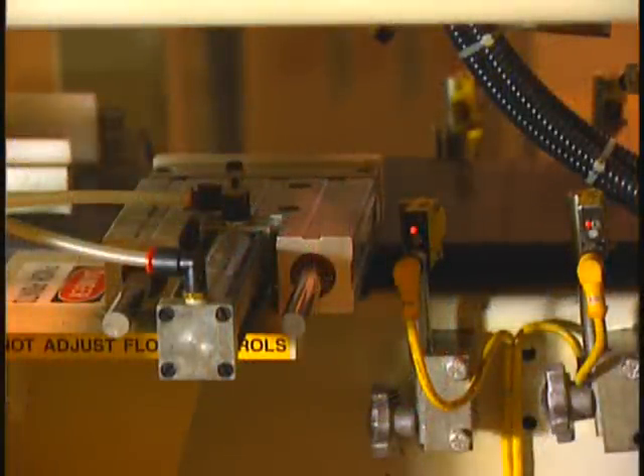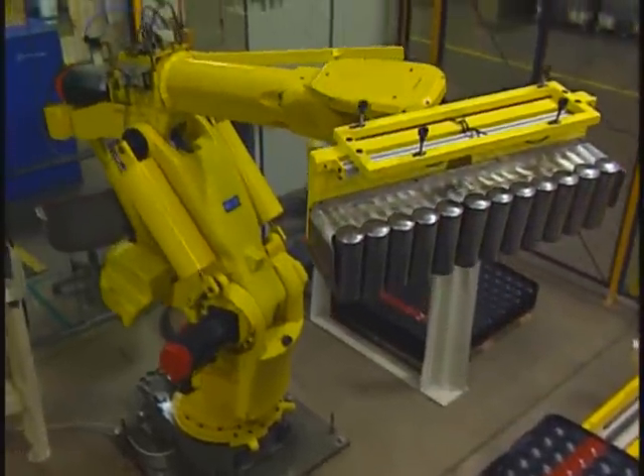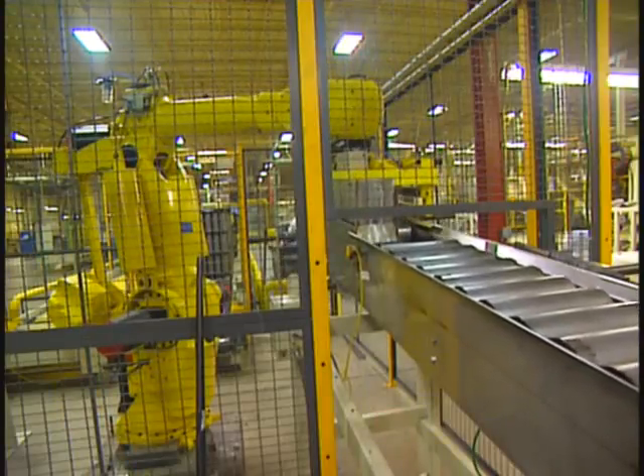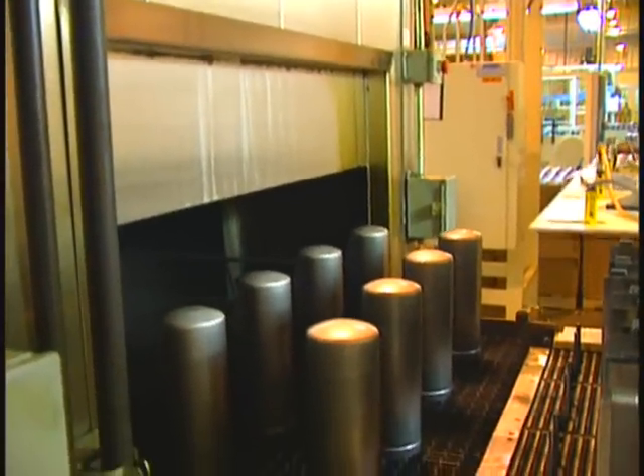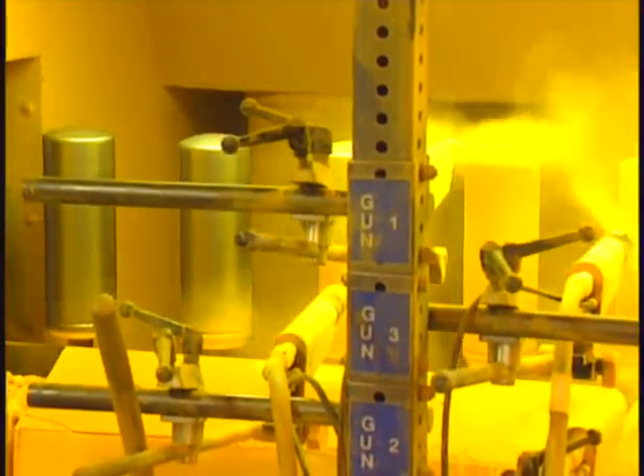This is one of many online specification checks made during assembly. The can, like the media, is manufactured to Caterpillar specifications. The one-piece design and the heaviest gauge metal can in the industry allows greater burst pressures and fatigue resistance than conventional two-piece cans. The cans are conveyed through a rust-inhibited detergent solution, rinsed, and then a permanent rust inhibitor is sprayed inside the cans. AFSI is the only filter manufacturer to use a spin-forming process to prevent potential leakage that can occur in two-piece cans. The open end of the can is closed around the top plate. Conventional crimped two-piece cans may leak or burst. The forming process is completed by contouring the spun edge over the top plate.